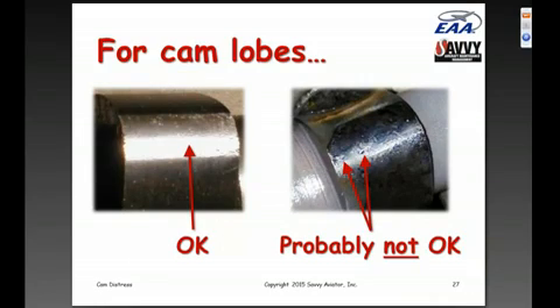And so the sharp pick test that Continental recommends in their service bulletin is basically a kind of a poor man's way to determine whether corrosion pits are deep enough that they might have penetrated that carburized layer. And that's the logic behind that guidance.